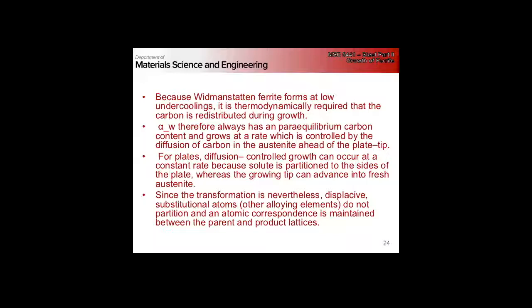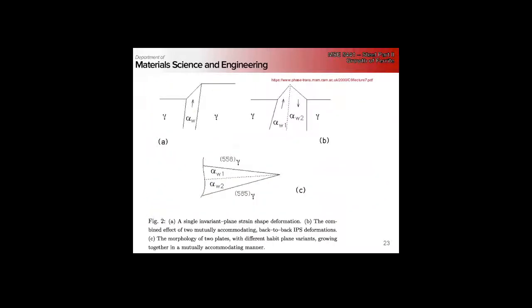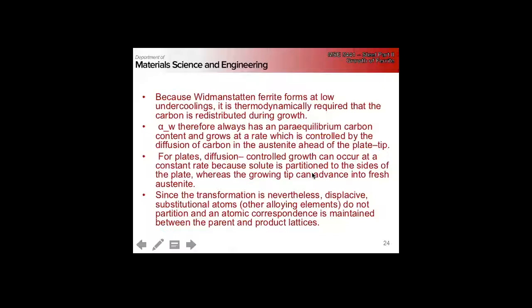So the analysis of this becomes similar to the growth of dendrites. The tip is always growing into fresh austenite. Our carbon can be partitioned out the sides, whereas our tip is always growing into fresh austenite.